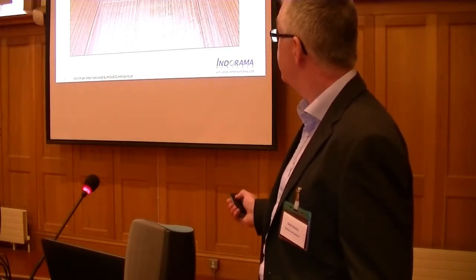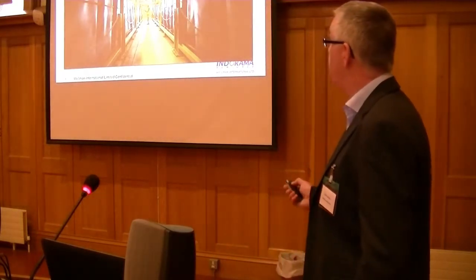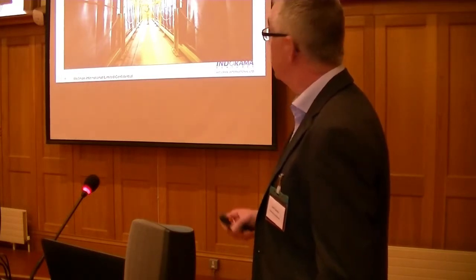We take all that material, we dry it, and we spin it through an extrusion process into the individual filaments of fibre. This image here is looking up towards what we call a spinneret or a spinning die. The material has been dried, melted at 265 degrees, and then pumped or forced through a metal plate with thousands of tiny holes. And that gives us the individual fibre shape and form. We then quench that very, very quickly, and that forms your solid fibre. We then take that fibre and we prepare it and finish it in our final process. So you can see the fibre, it's the white material here. We then take the spun fibre, we stretch it, we crimp it, so that gives it form and bulk and shape.